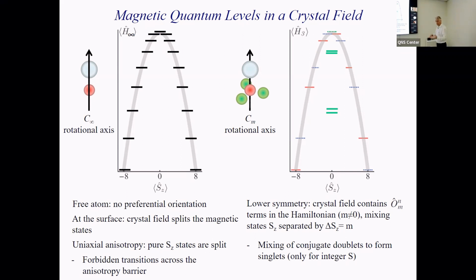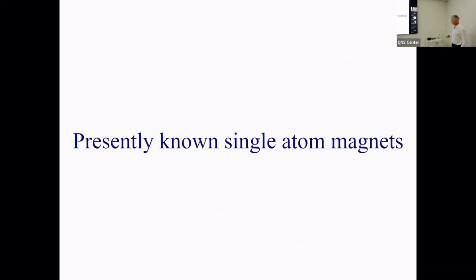And instead of being plus minus 6, they form a hybrid state, which is a superposition of plus minus 6. They also have some splitting, and the splitting basically defines with which probability you go here and then tunnel through this barrier and go on the other side. So the stability is given by the possibility to tunnel and to turn the magnetization around by this tunneling effect, which is shown here. And you have also, in addition, scattering with phonons.